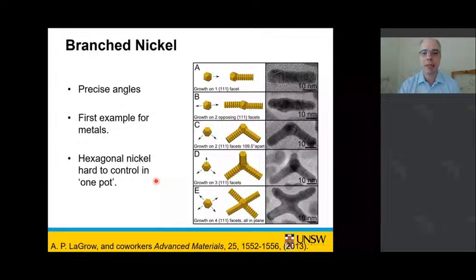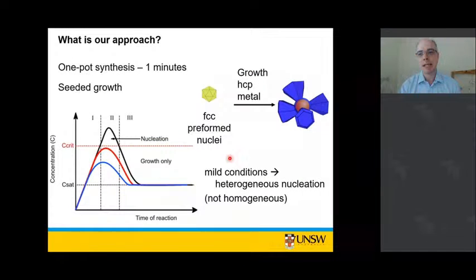So we wanted to use this mechanism a little bit more deliberately. So this is how we thought about starting to make these branched nickel structures. And essentially how we do it is we make some preformed face-centered cubic structure seeds. So typically for a lot of the reactions that we do, gold forms face-centered cubic crystal structure.